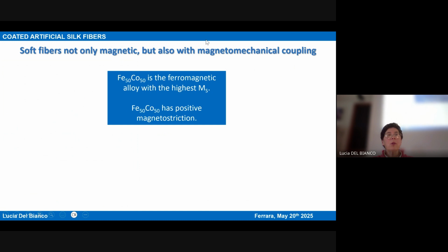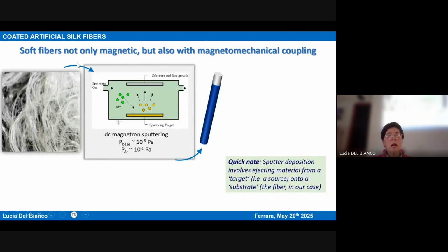And therefore, the idea was, okay, let's produce a mechanically soft fiber, not only magnetic, namely not only magnetoresponsive, but also able to exhibit magnetomechanical coupling. And this is why we selected iron cobalt, because this alloy is the ferromagnetic alloy with the highest value of Ms in the world. And therefore, it's good to have a high magnetic response. But it also has quite a high value of magnetostriction. It has positive magnetostriction. And therefore, we wanted to combine biopolymer and iron cobalt. And this was done by coating a thin layer of iron cobalt around the fiber.